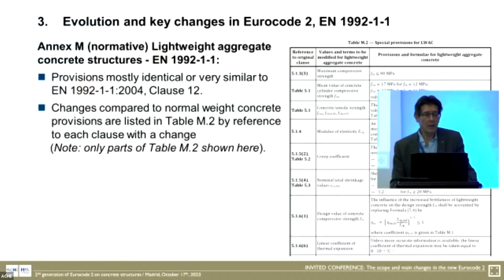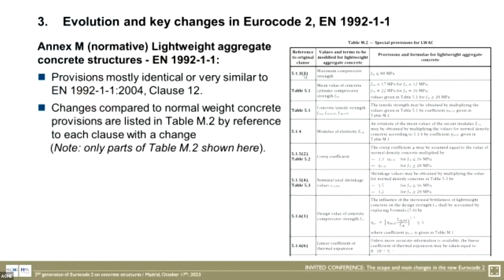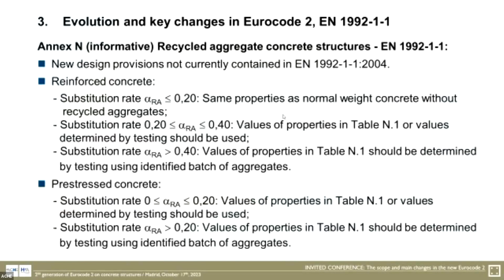Annex M, lightweight aggregate concrete structures. That's basically the same content as in current Eurocode clause 12. But again, we have changed the presentation and give all these provisions again in a compact table. So you see immediately in which clause or table there is a change and exactly what the change is. Annex N, concrete structures using recycled aggregate. Also, this is a new topic. Here we have created three categories. If you replace not more than 20% of the aggregates by recycled aggregates, we tell you you can use the provisions as they are given for normal concrete. For substitution rates between 20 and 40%, we give you formulae or the properties in the table, which I will just show to you. And if you exceed 40% substitution rate, we recommend that you determine these properties by testing.